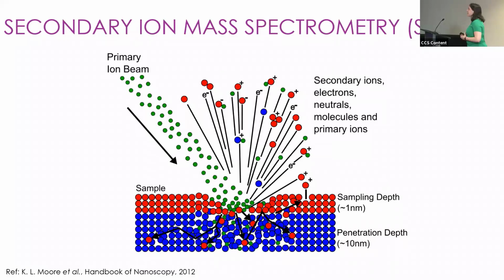So the technique is based on the principle of secondary ion mass spectrometry, or SIMS. With this technique, we use a finely focused primary ion beam to bombard the sample surface. This bombardment results in sputtering or removal of the top few atomic layers of the sample surface. We can collect the secondary ions that are emitted during that process and send them into a mass spectrometer, allowing us to determine what they are in terms of which elements. By scanning this primary ion beam over the sample surface, we can build up a chemical map of the elemental distributions contained within our sample. You can also see that this is a very surface-sensitive technique. We're only looking at the top few atomic layers of our sample surface.